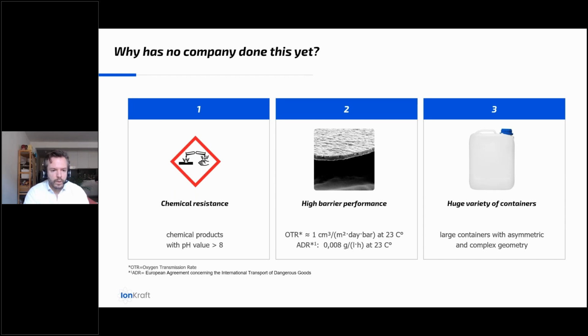But now the question, why has no one done this yet? Well, first, because common plasma silicon oxide barrier coatings, which are already out there, are not chemically stable enough for the application of chemical packaging. Second, because the very high barrier performance is needed, especially if you look at the transport of dangerous goods, which is actually regulated in the European Agreement concerning the international transport of dangerous goods. And you can see here they have a concrete number that you need to reach. You need to get to below that.